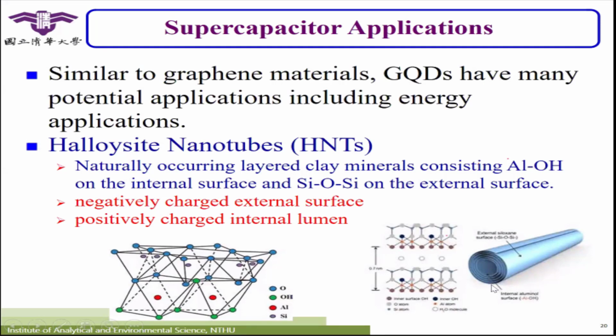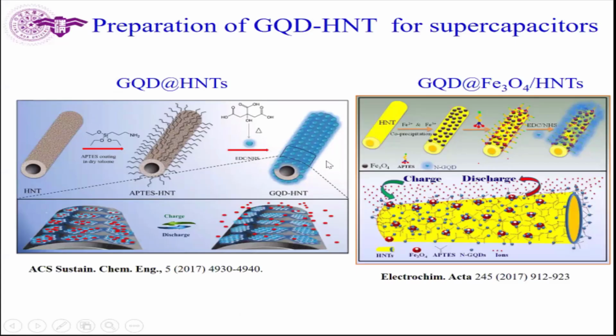And then we put the graphene quantum dots on the surface. Here is the case. When we put the graphene quantum dots on the surface and do the surface modification, we can see this is the halloysite nanotube. Do the test for surface modification, and then we can get some good absorption abilities on GQD. If you would like to recover or enhance their property, you can add some metal oxide, for example iron oxide or some other. So here is the case.